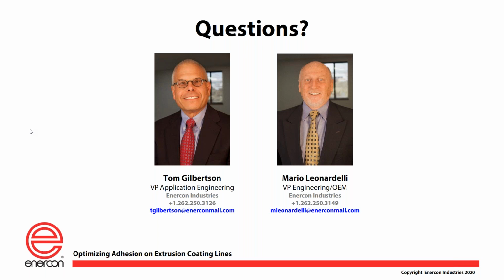Do you need to exhaust the ozone at the application point? That's a great question, and the answer to it is no, you don't. And the reason for that is, if you think about it for a minute, ozone is a very unstable molecule and it has a very short half-life. So it'll start recombining at temperatures of 350, 400, it'll start breaking down. Well, if you think about what the typical die temperature is on an extrusion coater, 500, 550, 575, those numbers are big. So really, you don't have to worry so much about having to deal with any ozone that escapes.